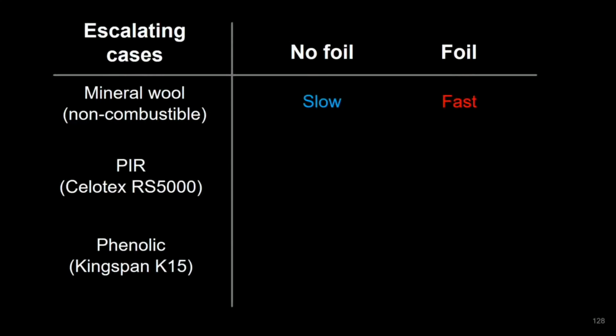For the mineral wool insulation, I found that the presence of a foil facer caused escalation to happen more rapidly when compared with the no foil case. Possible reasons for this, which are quite complex, are discussed, and they're slightly counterintuitive, it has to be said. They're discussed within my Work Package 2 report, but I don't want to go into it here.